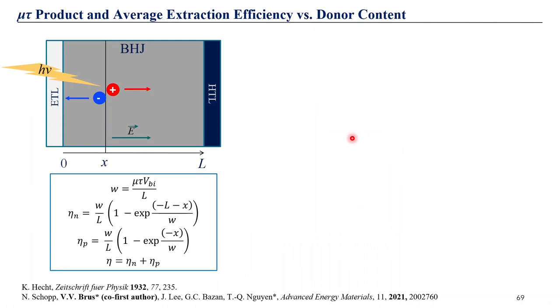The next question which is important to be analyzed is extraction of charge carriers. When we generate an electron-hole pair inside the bulk heterojunction, before it's collected by respective electrodes, these charges have to travel a certain distance through the active layer. And the probability of their collection can be calculated by the Hecht equation, which relies on such parameters as the mu tau product. So it combines the features of charge transport and charge recombination, because we have both mobility and recombination lifetime.